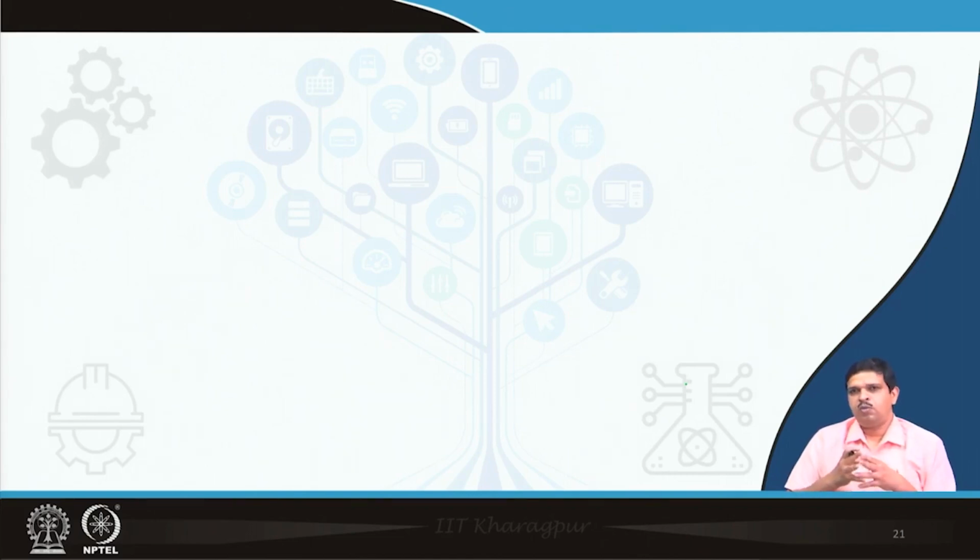Here we will discuss in more depth the polymerization by the Metallocene based catalyst, because that is the biggest beauty of the Metallocene catalyst: how we can get the stereoregularity of the polymers if we use prochiral monomers, which is not possible with other conventional polymerization like radical polymerization.